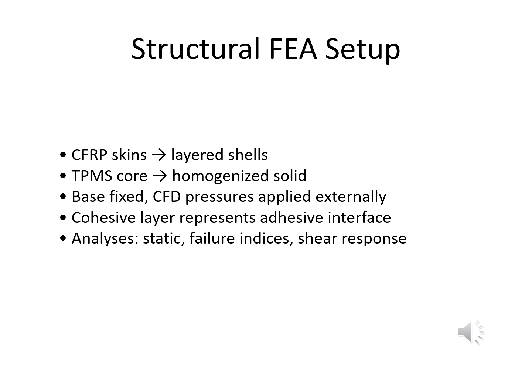The base of the nose cone is fully constrained to replicate the attachment point on the rocket body. We then apply the CFD mapped aerodynamic pressure, which provides realistic distributed loading. This modeling approach captures bending, membrane stress, shear transfer through the core, and potential interface failure. It also allows us to identify buckling modes and natural frequencies, ensuring the structure remains stable under aerodynamic and vibrational conditions. With this setup, we obtain a comprehensive understanding of how the nose cone behaves mechanically.